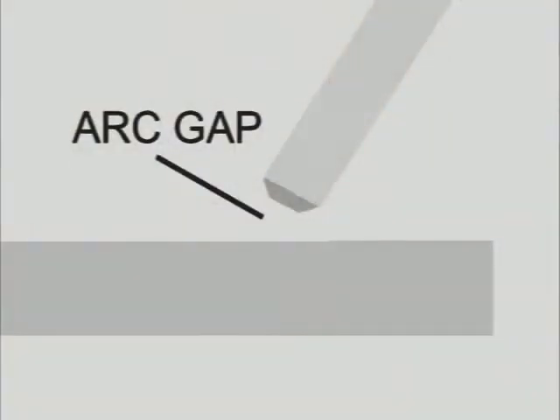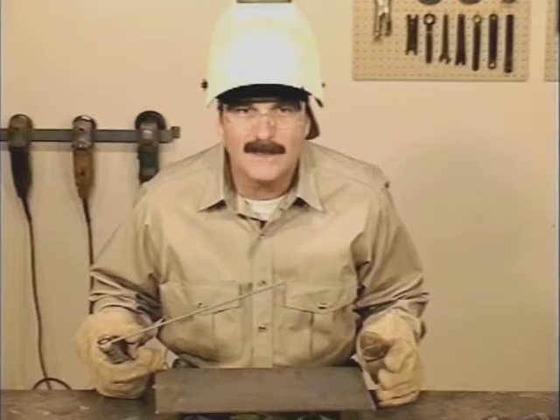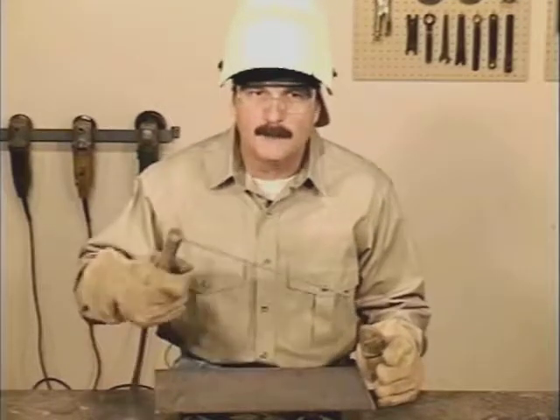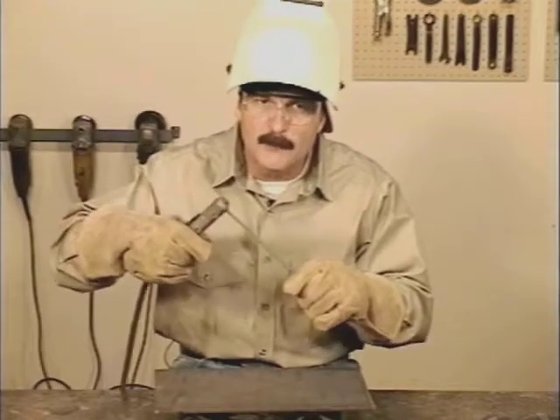During the weld, the tip of the rod is held up off the metal. This is called the arc gap. Having control of this arc gap is one of the first and maybe the most important things you need to learn. As you're moving along to build weld bead, the rod is being consumed, so you also have to be moving in. And the whole time you need to maintain a constant, uniform gap between the tip of the rod and the base metal.